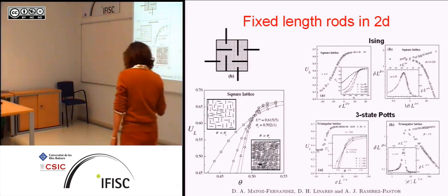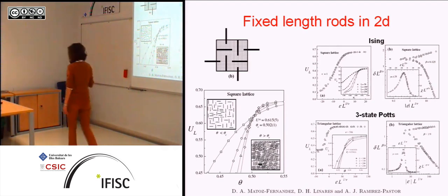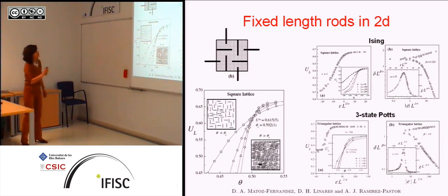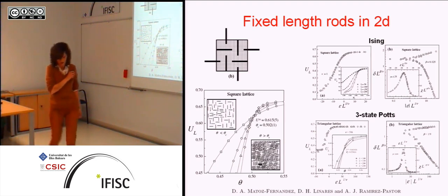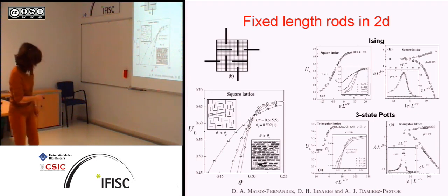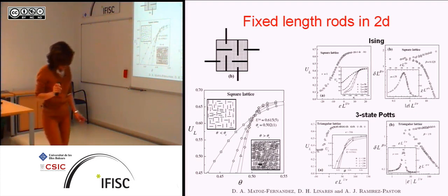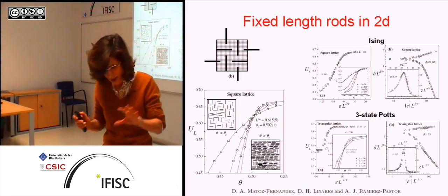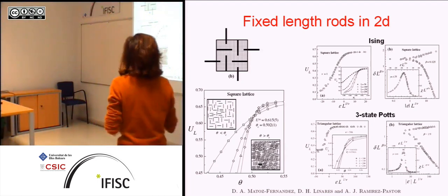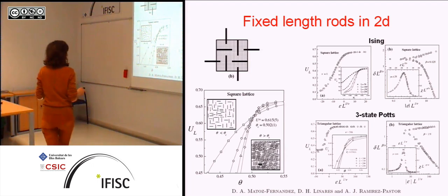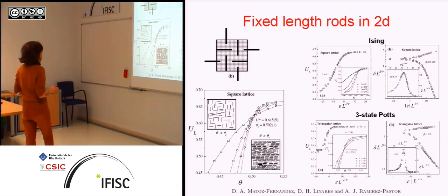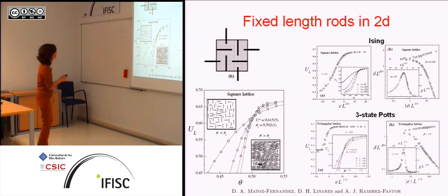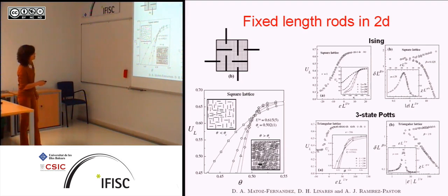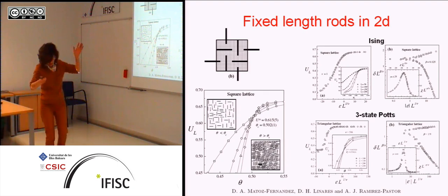Okay, so I want to simplify this because I really want to understand this a little bit better. So the first thing, I want to go to two dimensions, and this is not work of ours, this is work by a group in Argentina. This is just from one of their papers, and I just want to recall some of their results. In two dimensions, you simplify it even further, you put these things on a lattice. So these are rods of some length, but they're all fixed, so they all have the same length, on a square lattice. And of course, if you increase the density of rods, so this is the isotropic phase, you see as many rods pointing up as pointing sideways. They have no up and down, it's just two directions. These rods have no arrows.